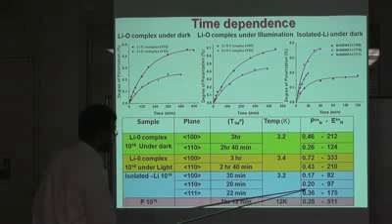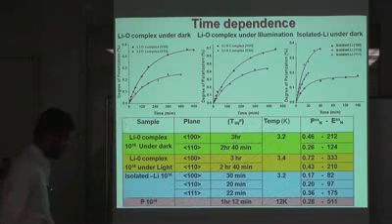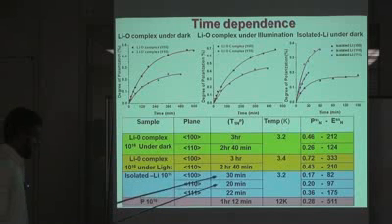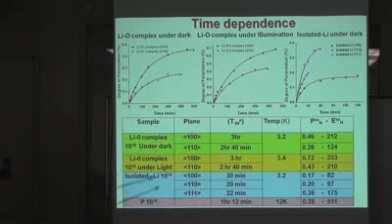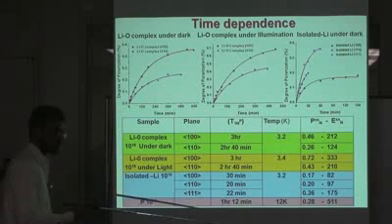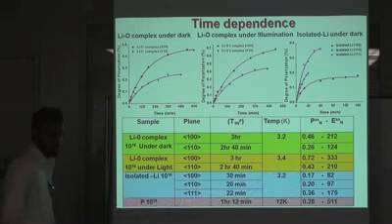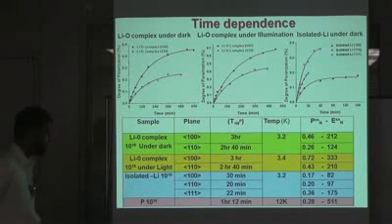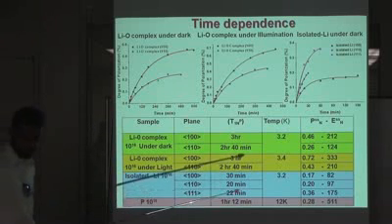in isolated lithium, with the 111 plane, 0.36%. Compared to phosphorus, both polarization values are higher, because the polarization value depends on the temperature condition. When we polarize at low temperature, we expect that higher polarization will occur, and we observe this phenomenon. This data was recorded by Hayashi in our lab.